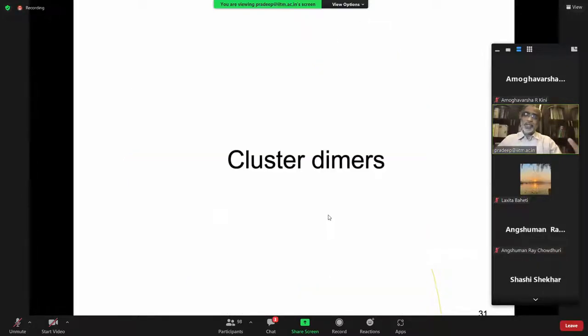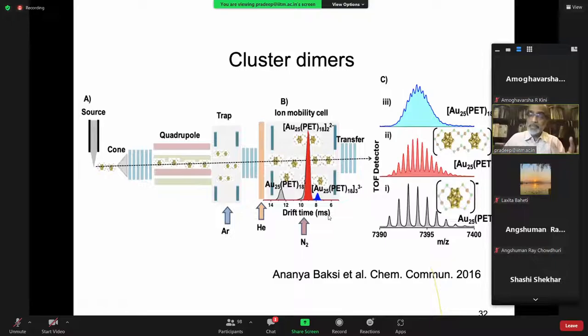So I told you that clusters are coming together and you do have a possibility of dimers. Can you see these dimers? Mass spectrometry allows you to see cluster dimers, and they in fact occur in solution. Gold 25, if you measure in the mass spectrum, you do see the dimer of it. You also see the trimer of it. You can do fragmentation or mobility and several such studies and prove that.